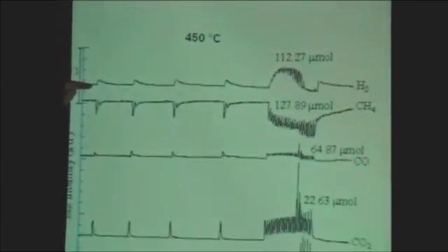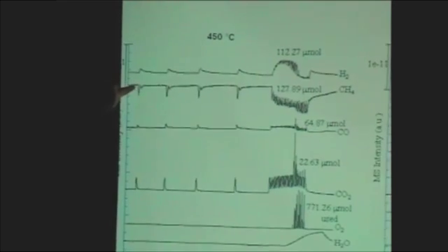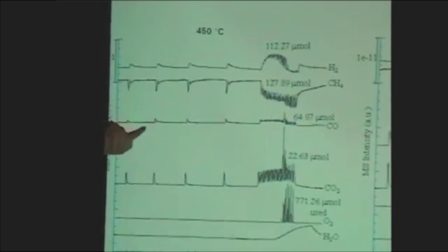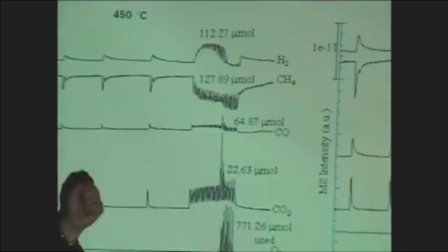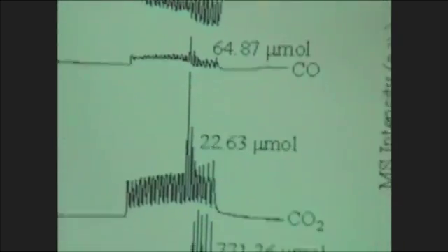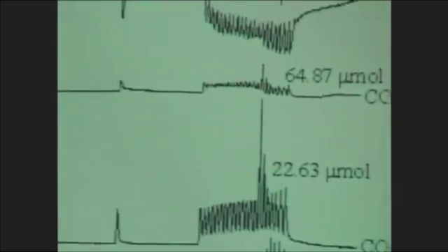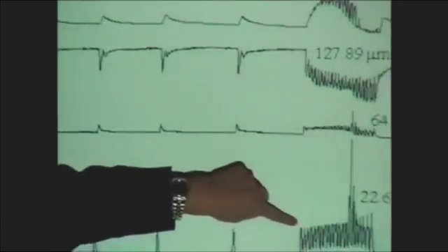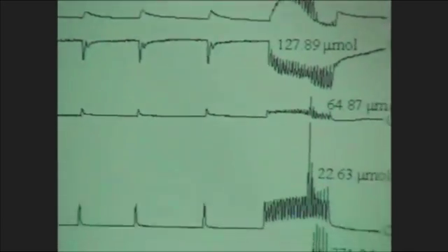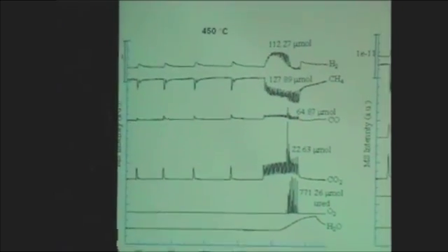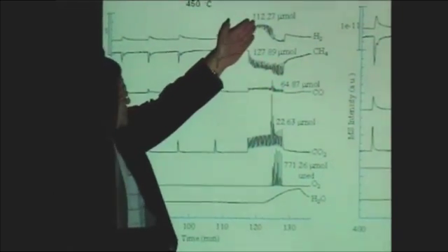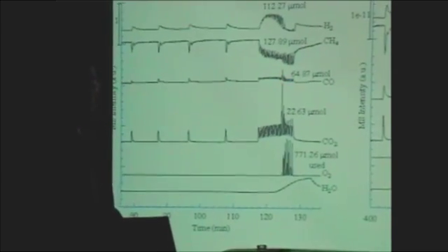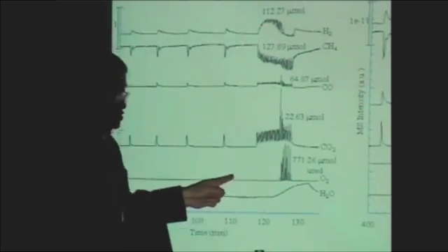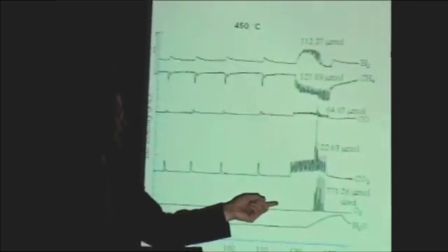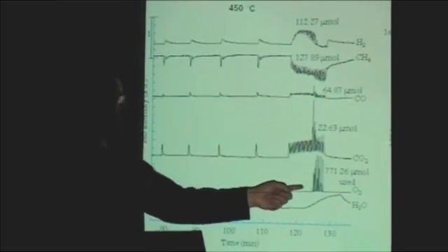Once we pulse through the oxygen here, we produce hydrogen. We deplete the methane. So you can see the mass spec profile going down, and we also see the CO formation. And as I pointed out, we have trouble controlling the amount of oxygen into the reactor. So as a result, I asked the student to quickly pulse a lot of oxygen. Every minute, pulse 3 or 4 oxygen pulses into the reactor, and to see how this continuous pulsing of oxygen affects the formation of hydrogen here. And as you can see, initially when we pulse the oxygen here, the oxygen does not break through. Some of the oxygen is apparently adsorbed on the catalyst surface.